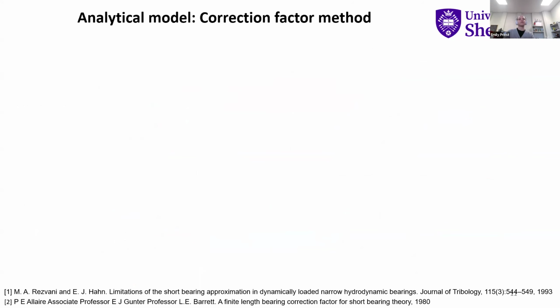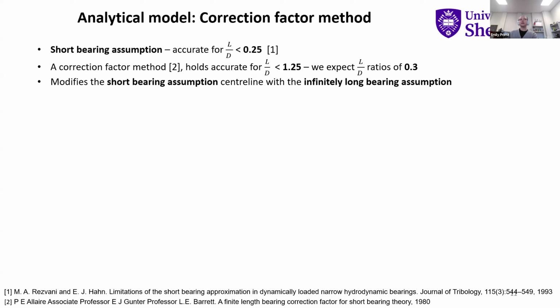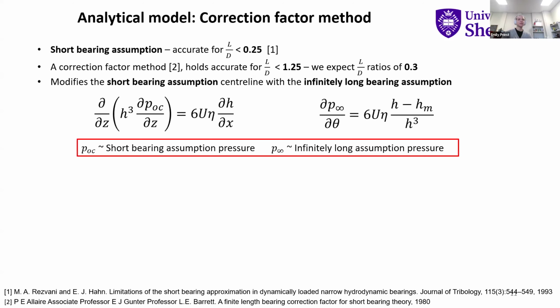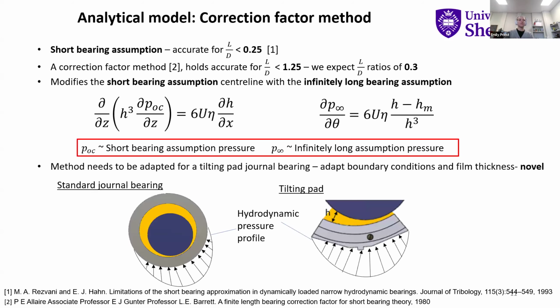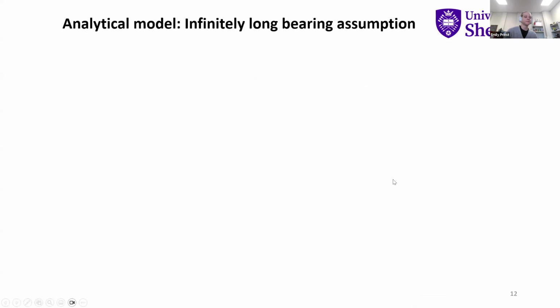Essentially we first had to find a pressure, and we do this by using the Reynolds equation, and we wanted to use an assumption on the Reynolds equation because normally it's in 2 dimensions. So what we do is use a combination of the short bearing and the long bearing assumption, which is called a correction factor method. And we have to adapt this method to be used for tilting pad journal bearings because, as you can see there, looking at those bottom 2 images, the boundary conditions are different, and the film thickness equation is different.